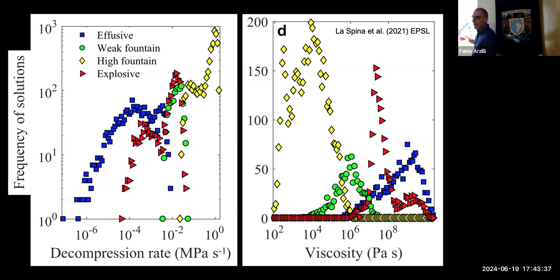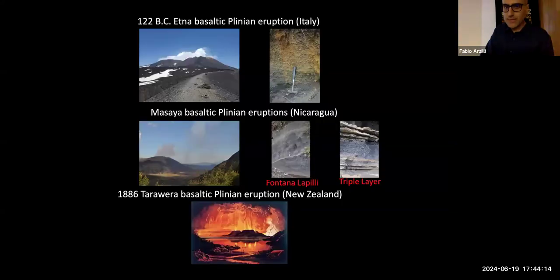This will increase viscosity high enough, around 10^6 or 10^7 Pascal second, where fragmentation can occur, feeding Plinian eruption. If the crystallization is promoted too much because the ascent is too slow, then this basaltic magma can reach equilibrium, meaning it will be highly crystallized, and highly crystallized means high viscosity, and so therefore it will be difficult to feed explosive eruption, but instead we will have effusive ones. So based on this information about the model, what we wanted to investigate, particularly, is how crystallization controls the magma rheology during ascent, during fast decompression rates and fast ascent rates.